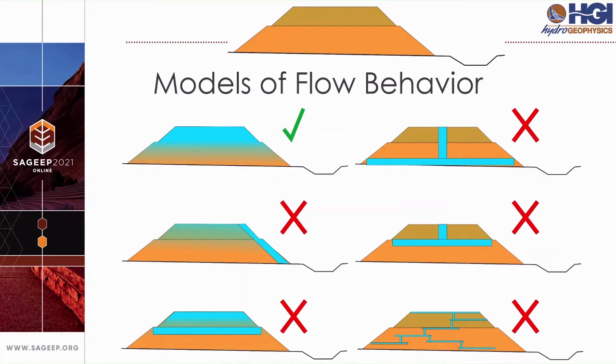Laboratory column studies where all flow is forced downward without opportunities of lateral flow reinforce this idea. However, at the field scale, uniform vertical flow is rare and the alternative is undesirable. The other 5 conceptual flow models presented here, while simplistic, give a glimpse into the complications that large rock piles can create, such as short-circuiting, mid-level water tables, shedding to the slope, or a convoluted fish ladder-like flow.